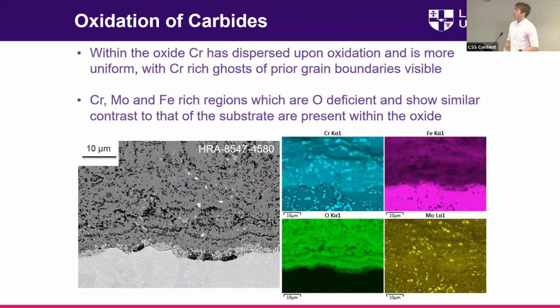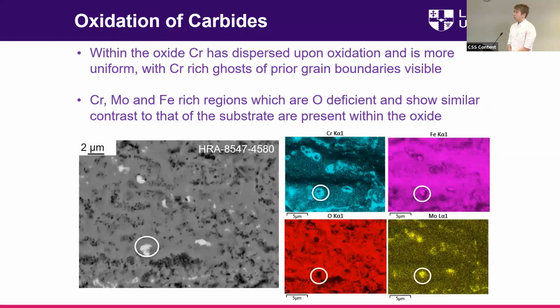So then if we take a little step back and have a look at the newly formed spinel layer, we can see that the chromium has begun to disperse a bit more throughout the spinel, where it's been oxidized. But you can see that there are some of these bright regions which show a similar contrast to the substrate below. If we take a quick closer look at these, we can see that there are these bright particles within the oxide. Within the same region, there's chromium, iron, molybdenum, but there's no oxygen at these particles. So that's suggesting that these are particles which haven't oxidized.